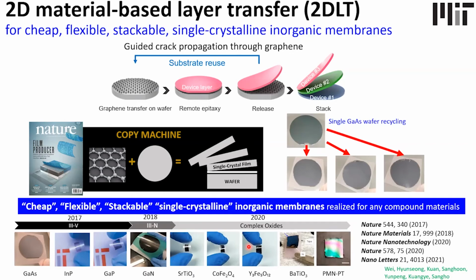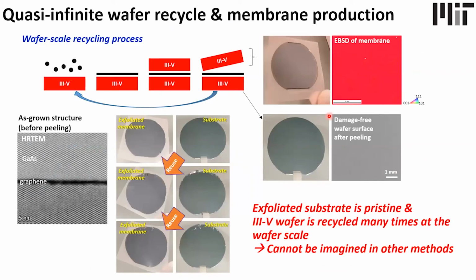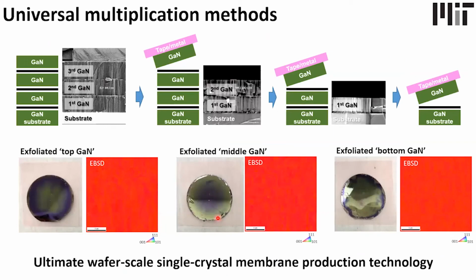So again, by growing graphene on III-V materials or compound materials, we are able to grow perfect single crystalline material. Then we peel off the entire film from the substrate. We are able to keep replicating this structure by reusing the single substrate. You are looking at the clones of a single crystalline gallium arsenide membrane, which is flexible and stackable, made by reusing the single substrate.